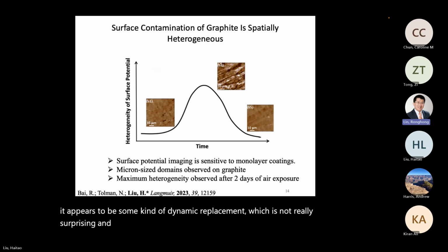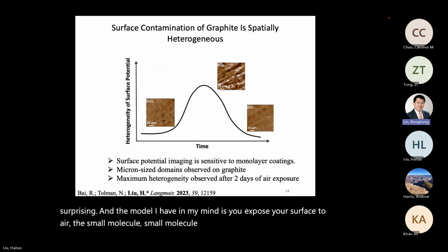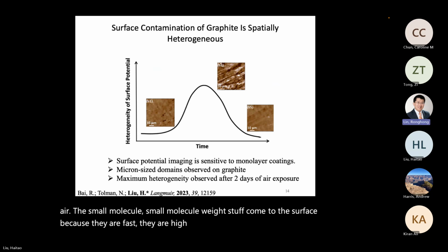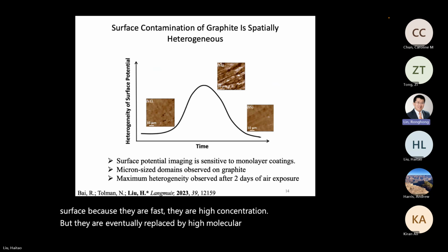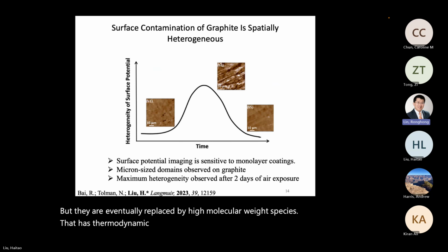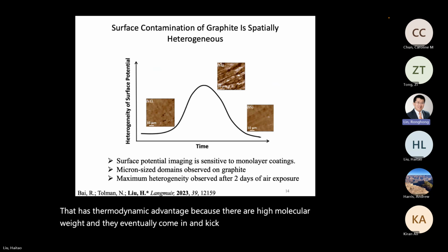And the model I have in my mind is you expose your surface to air, the small molecular weight stuff comes to the surface because they're fast. They're high concentration. But they're eventually replaced by high molecular weight species that have a thermodynamic advantage because they're high molecular weight. And they eventually come in and kick out the smaller things. So that's the model in my mind.